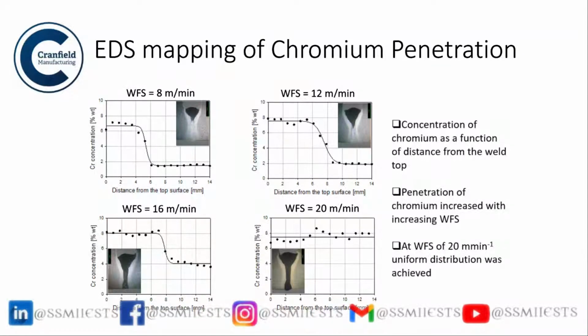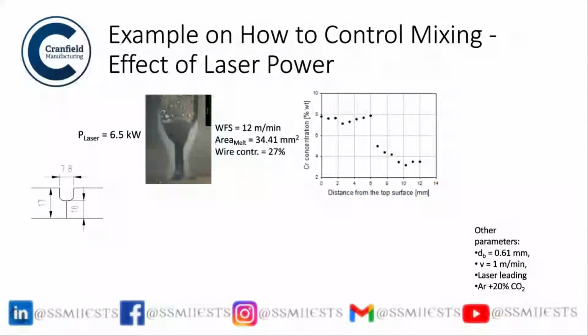Okay, so these are the chromium mapping or scanning of chromium using energy dispersive spectroscopy. And here you can see at a particular wire feed speed, you have a fully penetrated filler. And this is what you really need to know, I really need to decipher that for different types of power sources, how they interact in order to create a very effective joint. And also laser power can be significant in achieving the mixing.